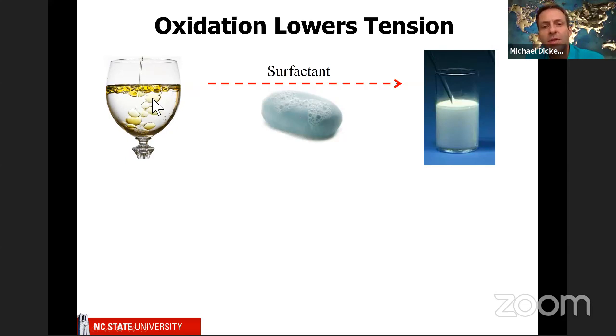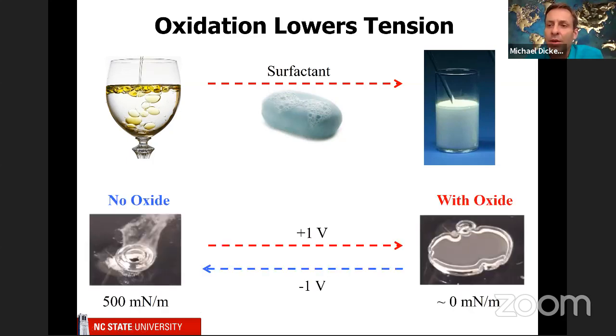So in this example, this is oil and water, but in our case, it's liquid metal and sodium hydroxide solution. Now, you know from experience, it's very easy to put soap into water, but it's very difficult to get it back out. In our case, we can apply 1 volt and get a huge change in tension and then -1 volt and make it go away. So this approach is completely reversible. And it's really hard to explain to people how remarkable this is scientifically.